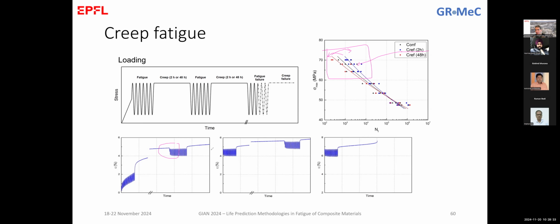Initial creep for a few hours, I'm trying to explain this simply. You remember the discussion that we had yesterday, how we can delay the crack. Now we have in the specimen a lot of multiple of these cracks here and there. When we apply some load for 2 hours, we create plastic zones in the crack tip. And these plastic zones are beneficial, you see, this behavior. When we let it for more, then we go to the last parts of the creep curve, and we create damage, significant damage due to creep. And this is the reason that here we go to the other side.